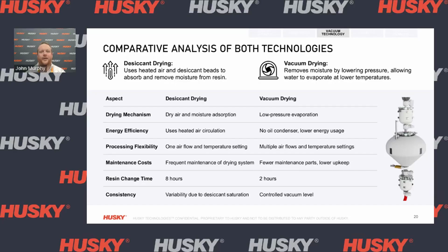Looking at resin change time, because there are 4 distinct phases, you are able to start loading a new material before you've finished drying your first material, reducing the resin changeover time down to 2 hours. And again, I'll go through this part a little more through my presentation. From a consistency perspective, we do see a relatively stable and controlled vacuum level as the means of reducing moisture.